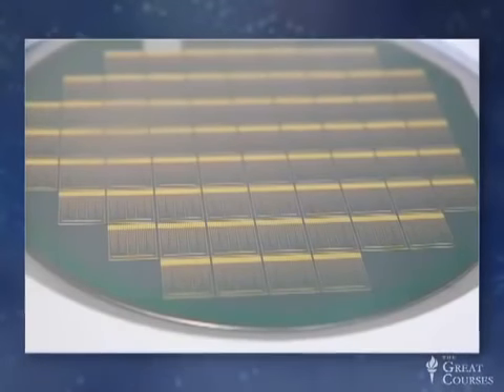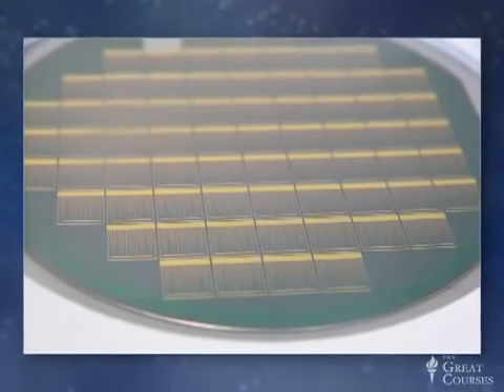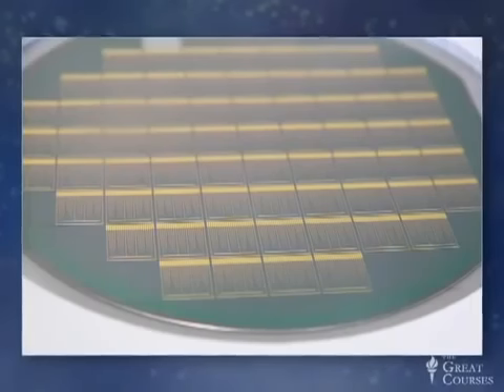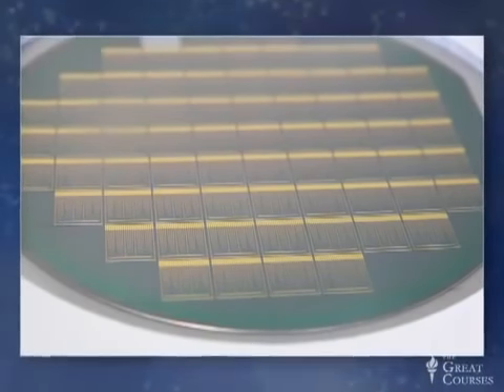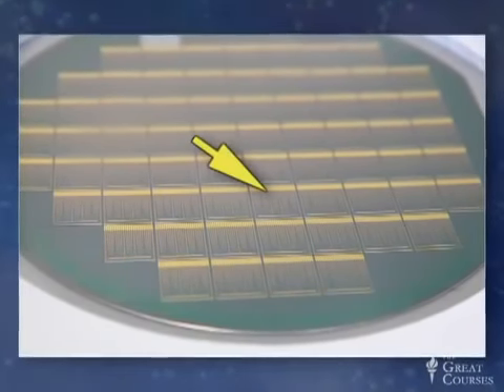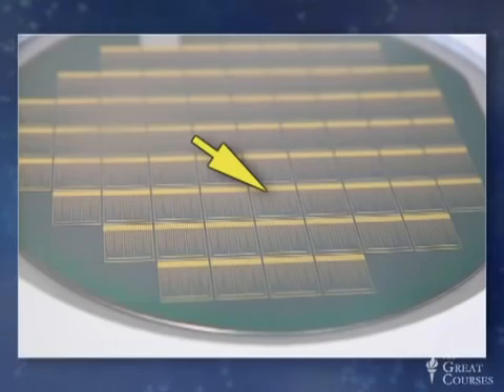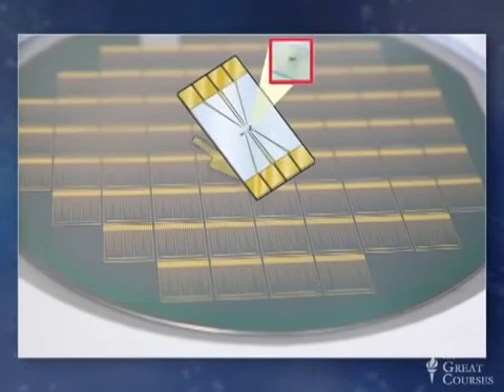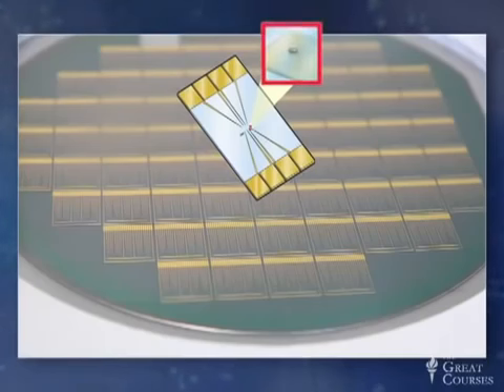So rather than making you squint at that tiny chip, we can look at a drawing so you can see the features more clearly. The yellow squares that you can see, those are made out of gold, and that's where we're going to contact the chip to read out the signal. The pointy things that you see are leads that separate the sensors from the contact, so we don't get any short circuiting. We put our sensors at the ends of the leads.